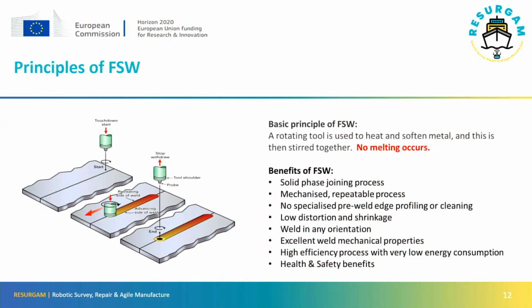It's a mechanized process, so it's done by a machine, so you've taken human variability out of the process, so you get a very repeatable weld. Because we have very little heat input, we get very little distortion, and one of the benefits is that because we have no liquid material, we can weld in any position. So we can weld vertically, we can even weld overhead. It doesn't cause us any problems because the weld is still solid as we're making it.